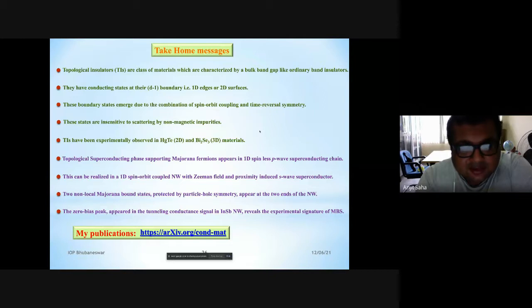And one has to define different topological invariants for that. Also, these boundary modes are insensitive to scattering by non-magnetic impurities. And experimentally, the 2D topological insulator was first realized in mercury telluride, and in 3D it was in bismuth selenide. So these are the basic take-home messages.